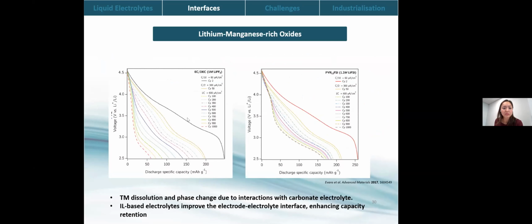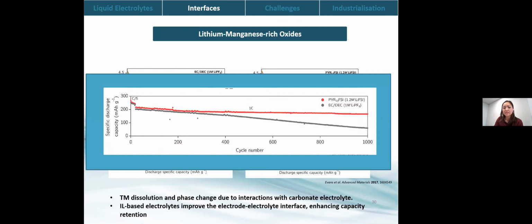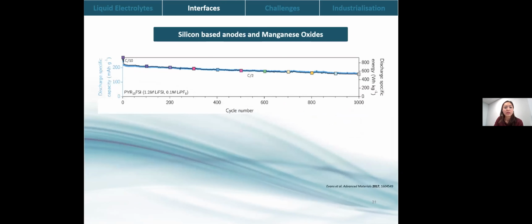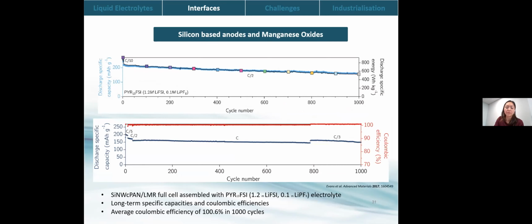They also tested the lithium manganese rich oxides in carbonates and purely ionic liquid electrolytes. And we can see that there is a huge loss of capacity when carbonates are being used, and when there are ionic liquids, the capacity is much better. And this is due to the transition metal dissolution. This change is due to interactions with carbonate electrolytes. And so the ionic liquid-based electrolytes improve the interface, enhancing capacity retention. And this is how good the cycling is with pure ionic liquids in a half cell. And this is with the full cell with silicon nanowires.